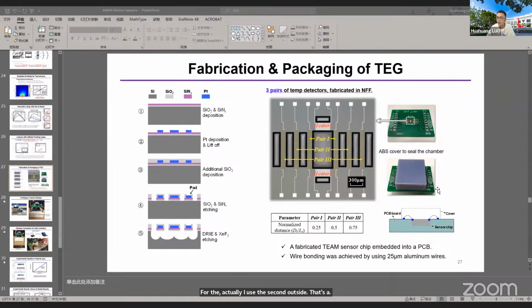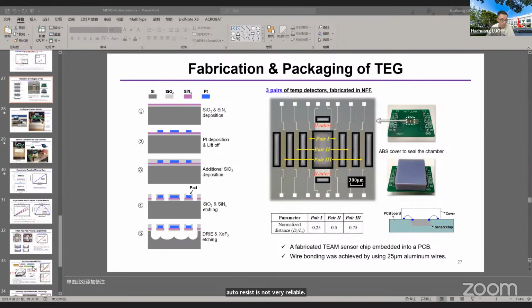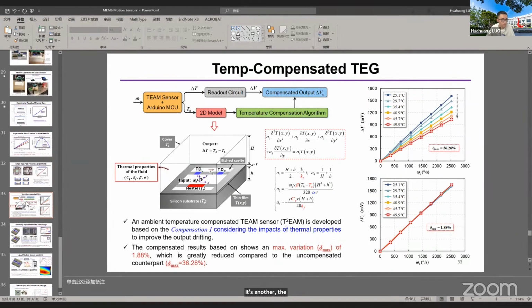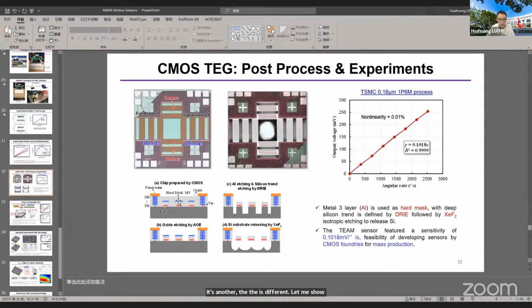Because you may know that during the deep etching, the photoresist is not very reliable. In CMOS type, the hard mask is different. Let me show you here. In CMOS type here, M3 means metal 3 layer. Actually, it's aluminum. I use the aluminum metal layer as a hard mask to etch the oxide.